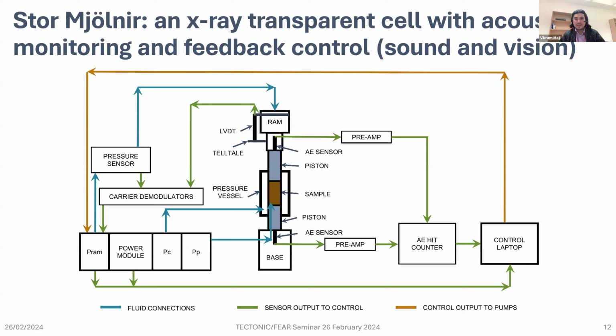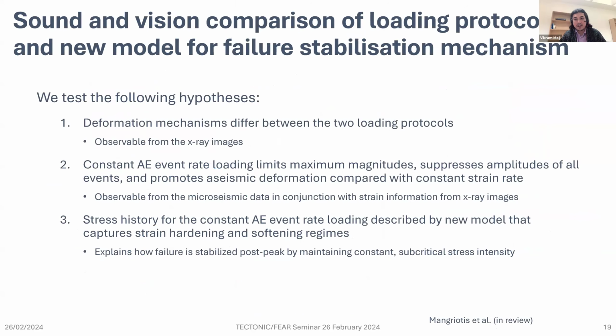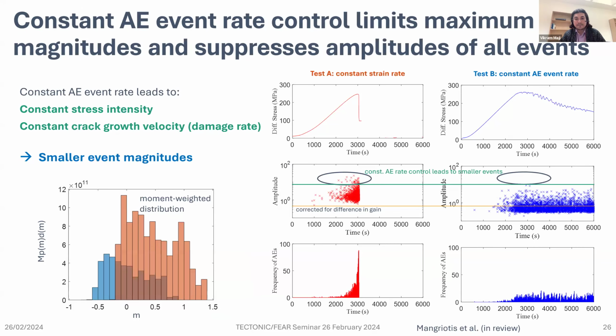Yeah, I'm just curious how you set up this experiment, and I have learned that you developed a protocol that captures the events and controls the mechanical instrumental aspect. Did you use any kind of threshold while filtering your acoustic emission data, to eliminate the noise and separate out your actual events? And how do high magnitude and low magnitude events fit into this constant AE rate experiment, perhaps with high magnitude events in the ultimate stages of breaking, peak failure, or low magnitude events during the compaction? How are they distributed and how can you link those phenomena in your experiment? Could you please explain?